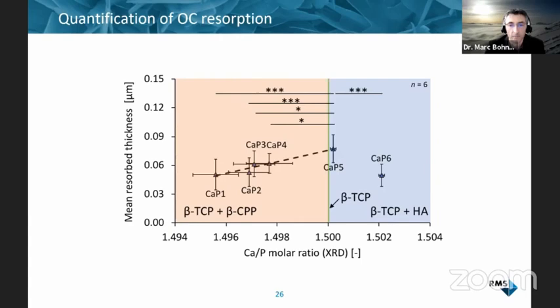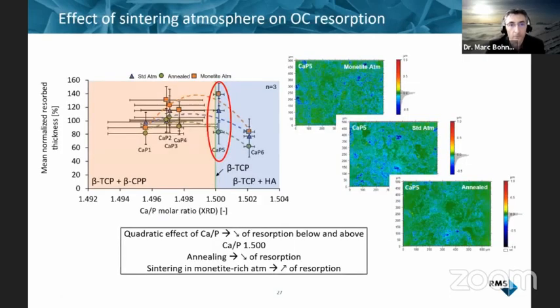resorption of beta-TCP. And the ISO standard says that you can call your beta-TCP pure beta-TCP if you have up to 5% impurity, like pyrophosphate. So this is very important, when comparing calcium phosphates, to control this calcium pyrophosphate. We also realized that the sintering atmosphere affects the result. I'm not going to go too much into the detail, but the standard points are the blue triangles, but when we did the sintering in the monetite-rich atmosphere, we had a higher resorption rate, and if we did it after calcining the surface at 500 degrees to form calcium oxide, we had a drop.